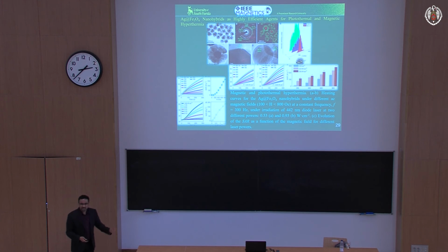Okay. My students started playing with this system. They actually use the AC hyperthermia to get to 40 to 45 degrees Celsius, and then they turn off the magnet. They use a laser to keep the temperature stable in that regime. So they perfected this way of dual functionalization.